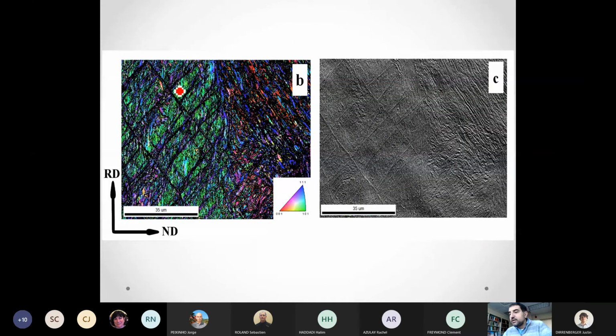map. And here's another example just to illustrate the point where you can see that the deformation in this core where the carbon content is 0.4 is not uniform. In fact, it's localized into these bands. And because of the high deformation in the bands, we cannot index them very well, but the deformation outside the bands is relatively low, so we can index it well with the EBSD.